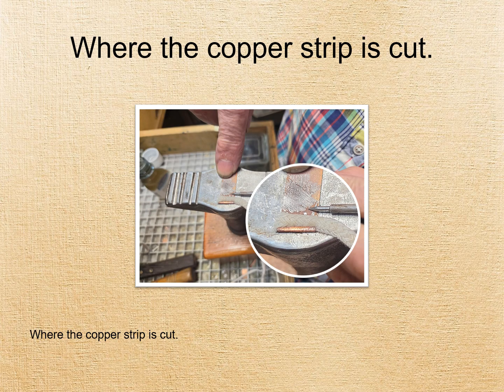The decision to make a type 2 aglet means you cut the metal strip about 3 millimeters from the far side of the cord, so you can use the end of the anvil to make a second curve to hold the cord before you do the final bending. If you're making a type 3 aglet, you want to cut the copper about 2 millimeters from the far side, so you have just enough to wrap around the aglet.